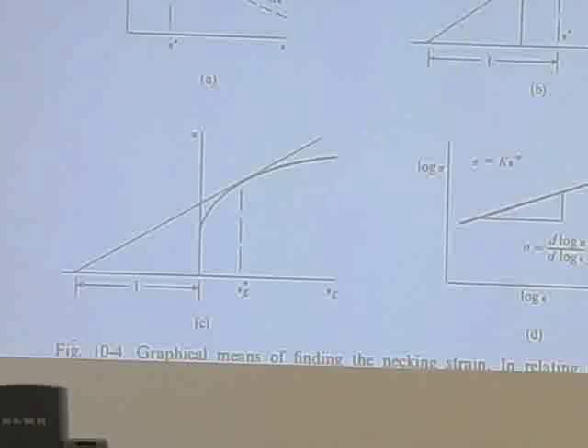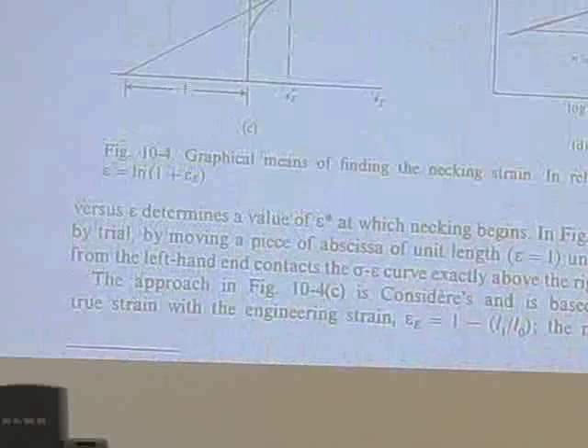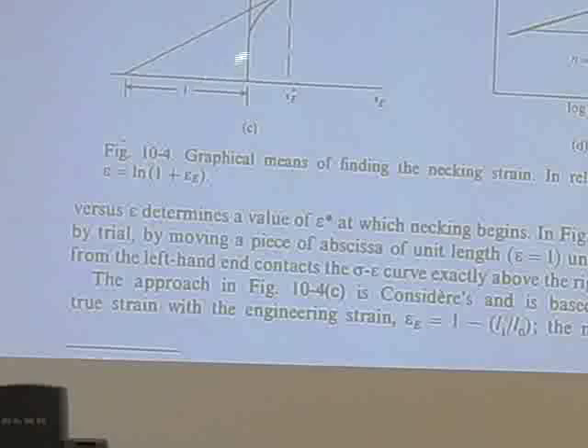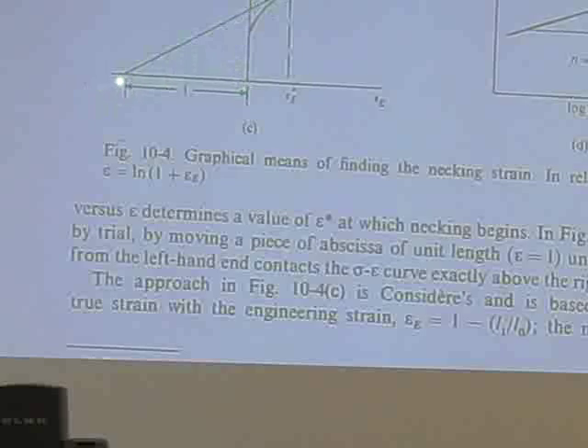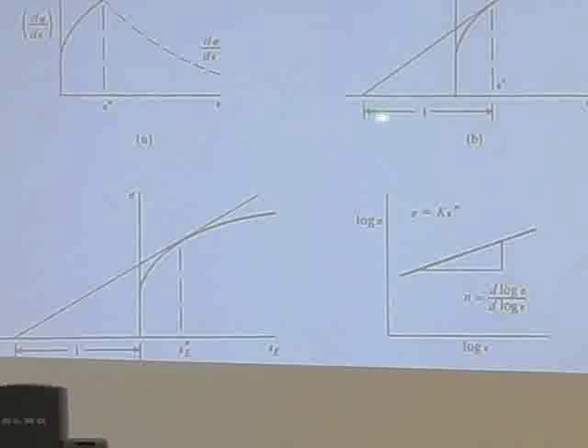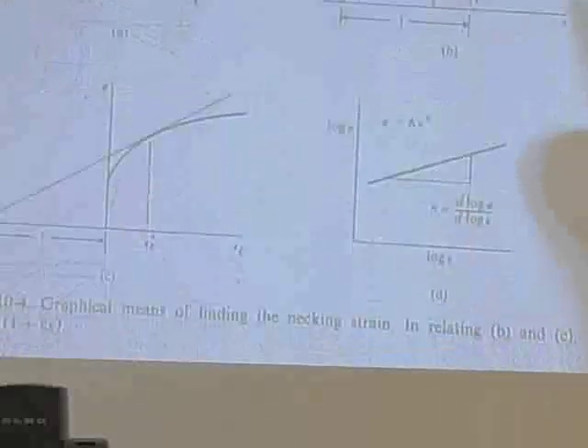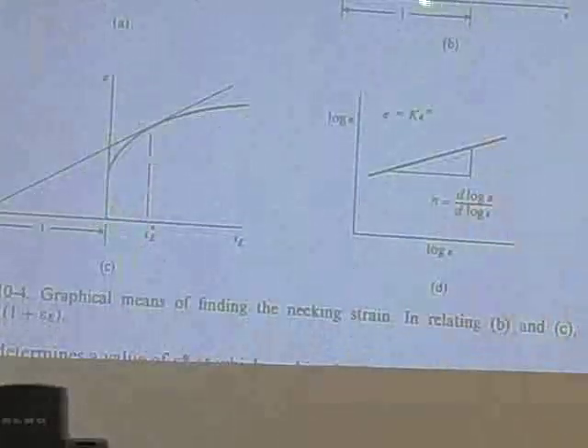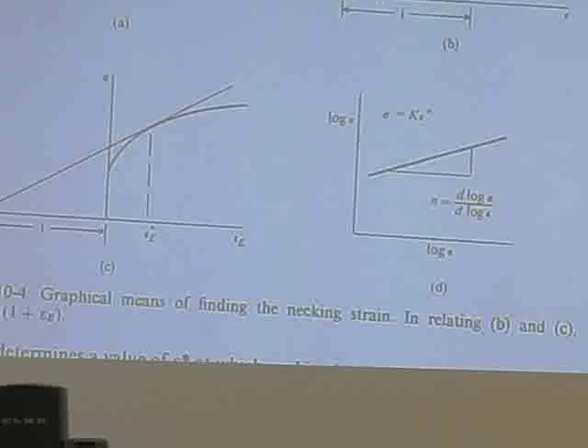However, there's something called the Considere construction, which I mentioned once earlier, but I haven't emphasized. You take a stress strain curve, this is an engineering stress strain curve, and you can prove that the true strain is the log of 1 plus the engineering strain. So this is 1 plus the engineering strain, and you take the tangency or the secant back here at a strain of -1, draw a straight line, and that will give you your engineering strain when necking starts. If you want to do it in true strain, it turns out this is just a distance of 1. So the other one down here was -1. The distance from the necking strain to where you need to draw your secant is basically just a unit of 1, and you can prove that by transforming engineering strain to true strain.